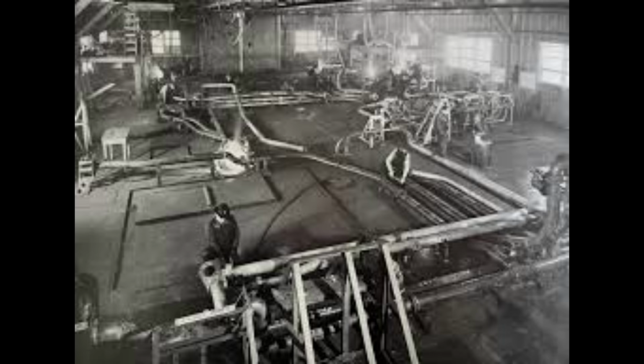Plates in which brittle failures originated had a 21 joule transition temperature of 15 to 65 degrees Celsius, with a mean of 40 degrees Celsius. Translation: the steel used in Liberty ships became notch brittle, susceptible to sudden fracture when a crack or notch was present at temperatures well above freezing. Such steel would undoubtedly have been notch brittle during winter and spring in the North Atlantic.